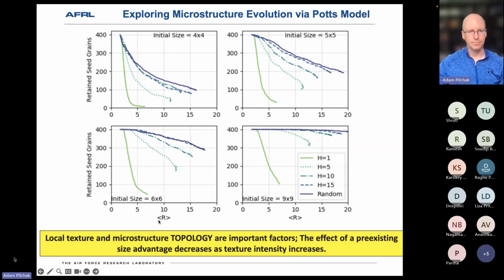And so what we're plotting is the average grain size of the retained seed grains here. And so with really sharp textures and minimal size advantage, it's very likely for those seed grains to get consumed and disappear. Let's see, if we go all the way to the 9x9 case, in all except for the most unrealistic sharp texture, that size advantage makes most of the grains persist for realistic texture intensities. And there's some kind of continuum and transition between those.